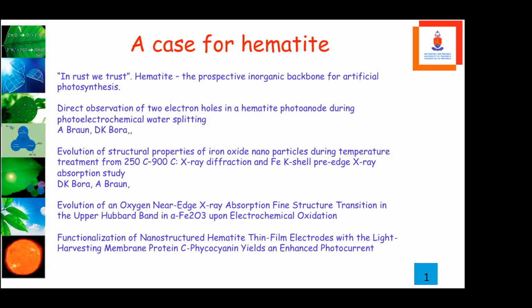Another experiment by my colleagues DK Bora and A Braun, using the X-ray diffraction facility, were able to publish this work on evolution of structural properties of iron oxide nanoparticles during temperature treatment at the Synchrotron facility. And the next one was evolution of oxygen near edge X-ray absorption fine structure, transition in the upper Hubbard band, where we were using the material iron oxide for electrochemical oxidation.